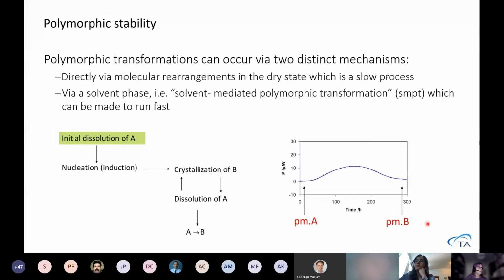Then we can also study the polymorphic stability to see if polymorph A goes to polymorph B. We can follow that over time by just putting them into an ampule in the calorimeter and following the process. If we just put the powder in dry, it could be quite slow, but it can also be done via solvent-mediated polymorphic phase transformation, where we make a slurry, and the least stable polymorph typically will be dissolved, and then it will crystallize into B. When this has disappeared from the solution, we dissolve more of A that crystallizes into B. By doing this with a slurry, we can force A to go to B, and we can make it happen faster. So we can follow this process over time, going from one polymorph to another.